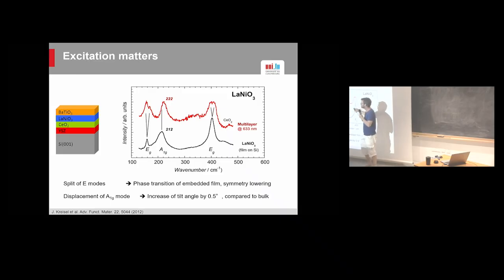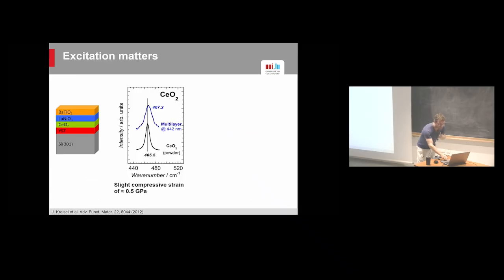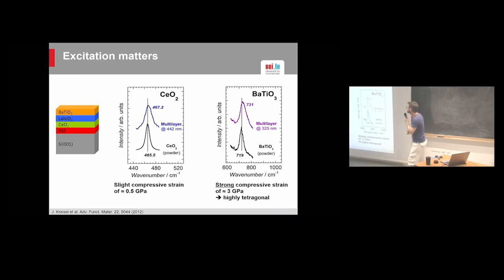Okay. So conclusion: we have strain that we can quantify more or less like that just by checking how this mode shifts, and we have a phase transition that's clearly indicated by the splitting of those modes here. And the same thing would go for the cerium oxide layer and the barium titanate. You can then try to essentially interpret this Raman shift in terms of stress that the layer is under. Okay.